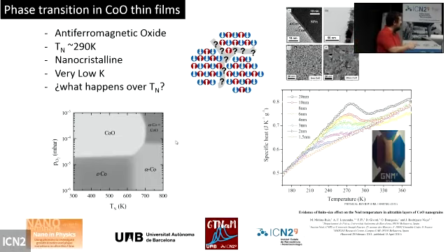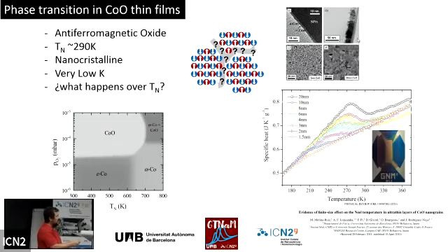This is the phase diagram. Typically, we grow the cobalt oxide by oxidizing cobalt in flight, evaporating metallic cobalt and oxidizing it during flight. And we were getting that kind of sample, with vertical columnar growth. And here you can see one example of nanocalorimetry in that case, where we can find the Néel transition that is related to the order-disorder transition from antiferromagnetic to paramagnetic phase.